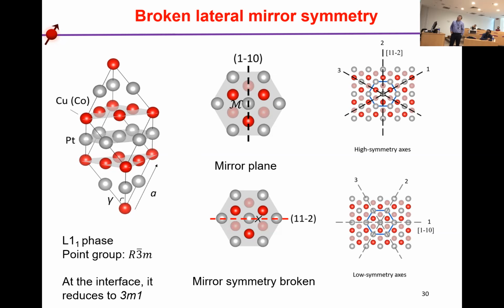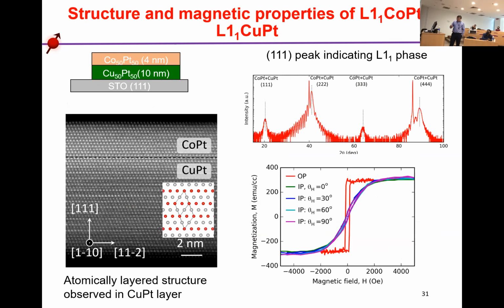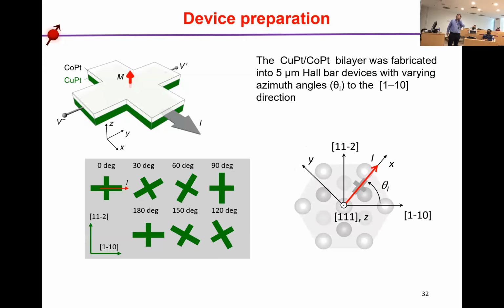So then we make the materials by sputtering. From here we can see we get good L1_1 copper-Pt, characterized by the L1_1 superlattice peak and also the TEM structures. So very good perpendicular anisotropy, and the in-plane is isotropic. Then we make the devices along different directions. Here the [1-10] direction refers to the low symmetry direction.